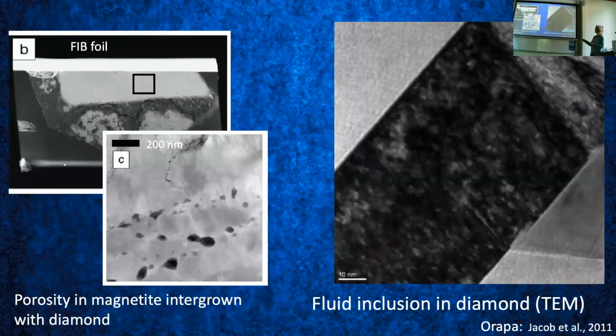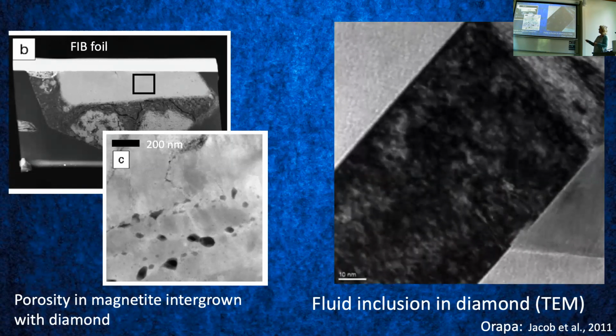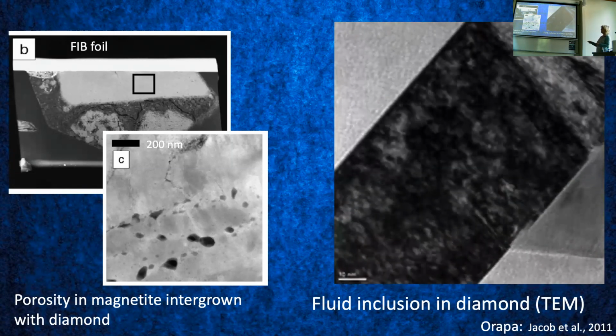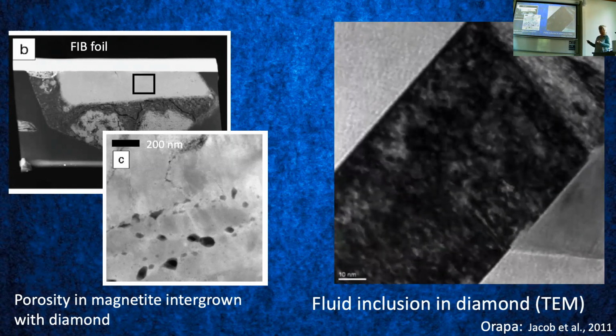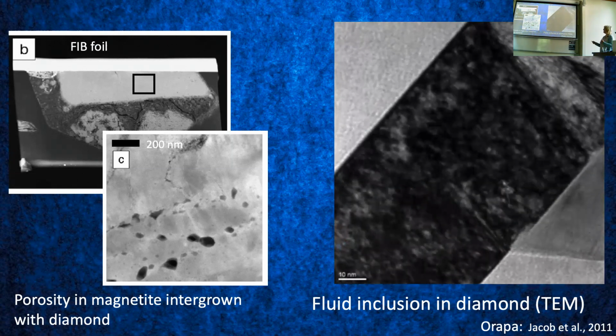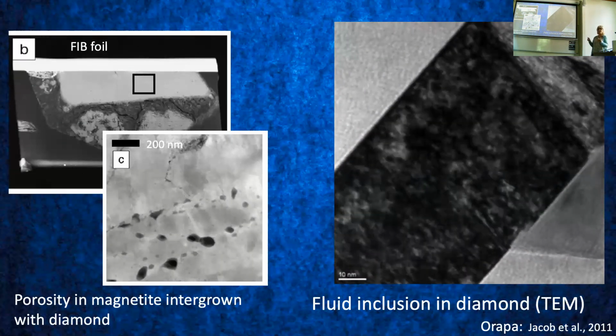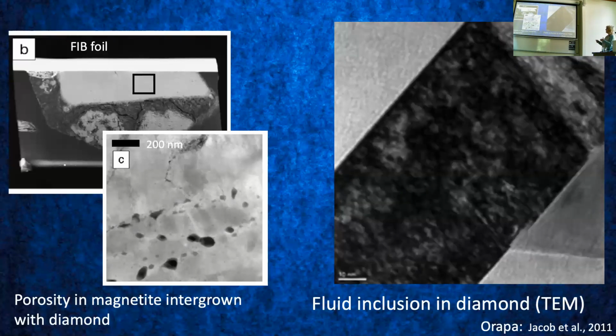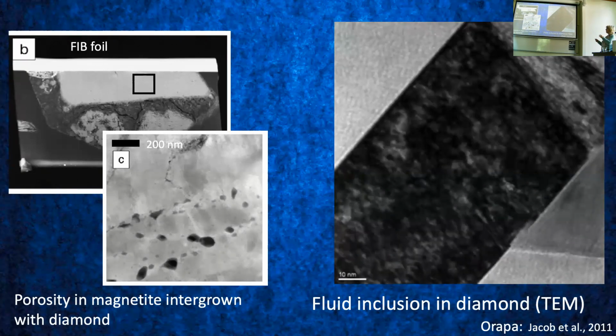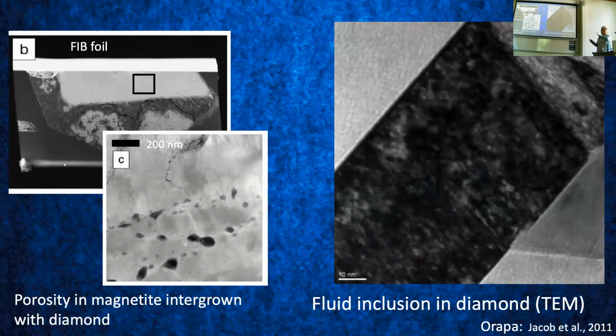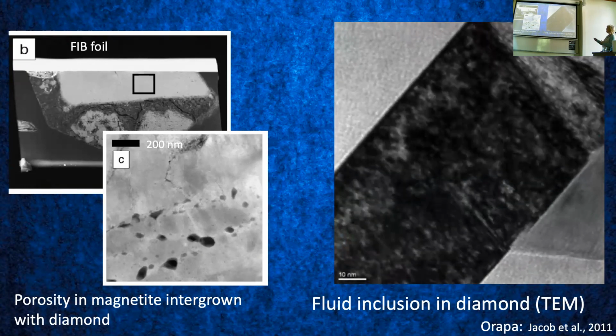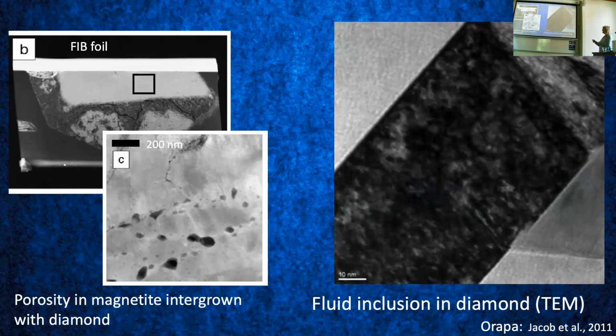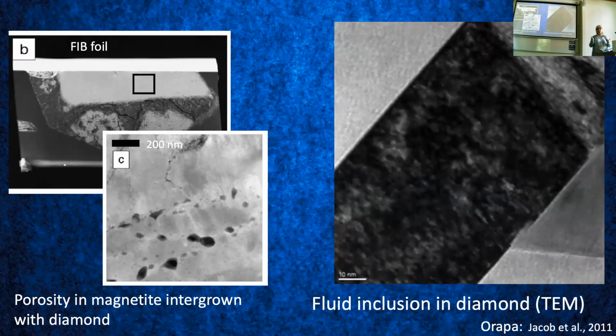On the left here is a focused ion beam foil cut through one of those diamonds that had a magnetite inclusion. When you get a close-up of this magnetite, you can see that the magnetite also has a lot of pores, which were probably fluid filled. Sometimes one is lucky enough to still have a cavity in one of these diamonds where we can still see the fluid. So this is basically the diffraction contrasts that are oscillating under the electron beam. I took 10 or 15 pictures and made a GIF out of this. So you can see that this is fluid here, and there's a little bit of mineral there. That's as far as you get with TEM to say what it is, because TEM is not exactly the method to analyze the fluid from.